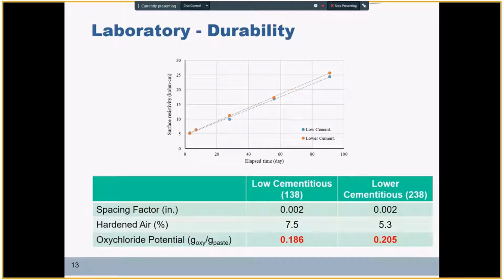But the oxychloride potential data we see here is actually a factor of binder composition, specifically the amount of fly ash in the mixture, not the total amount of binder in the concrete. So potentially, if we had more fly ash in these mixtures, we wouldn't see these two red numbers. But anyway, these two numbers do not have anything to do with the binder content, so no worries regarding the binder content here.